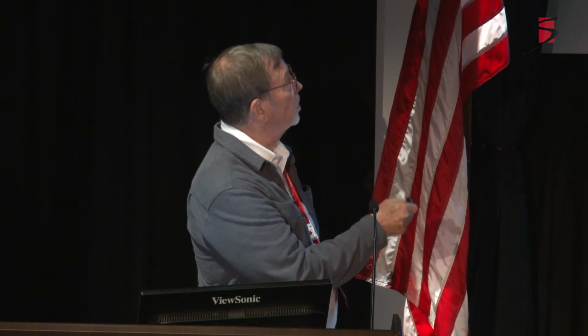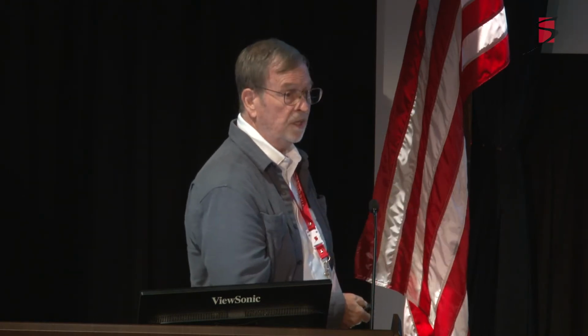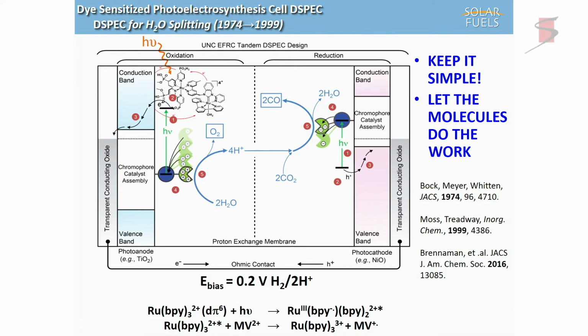I've got to have a light absorber there, but I also need to have a catalyst for water oxidation. One of the best places to look for that is also with ruthenium, with its multiple oxidation states. So that was a thought. If we're going to do it, we have to be careful. TiO2 is okay, but the potential that comes out of the electrode, if you're trying to go to a second electrode and reduce water to hydrogen, it doesn't work. You're off by 0.2 volts.